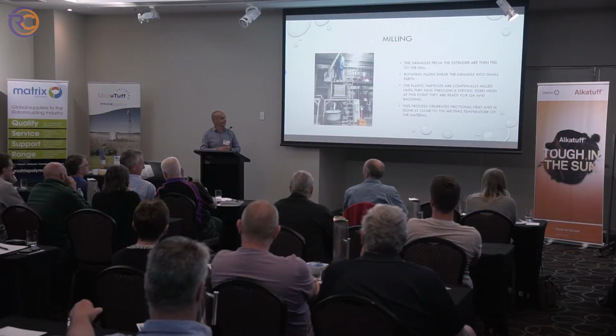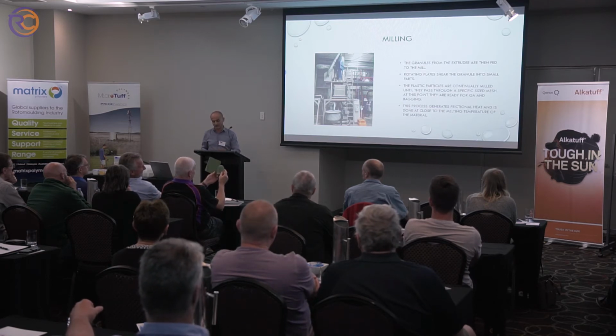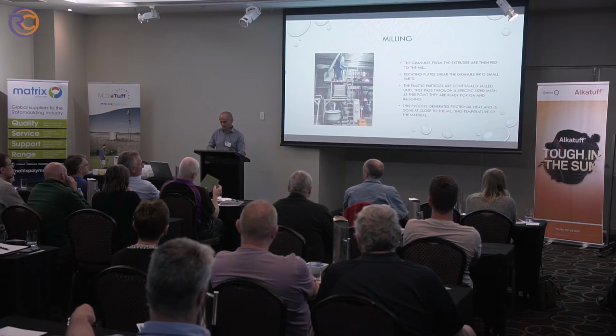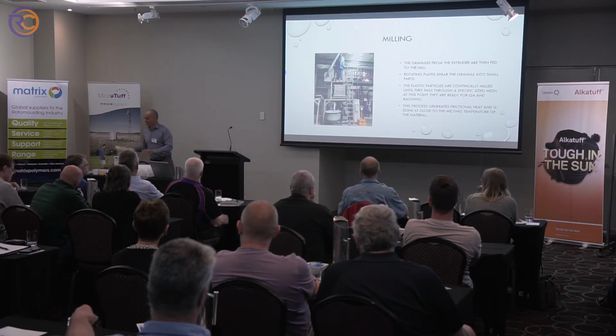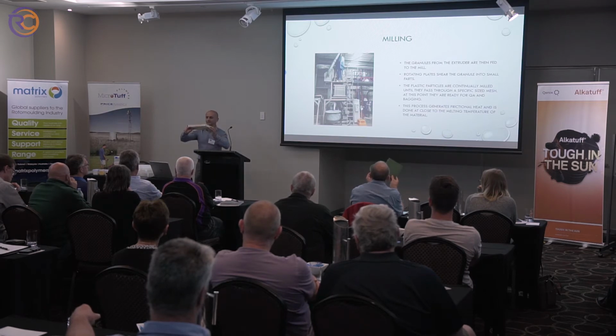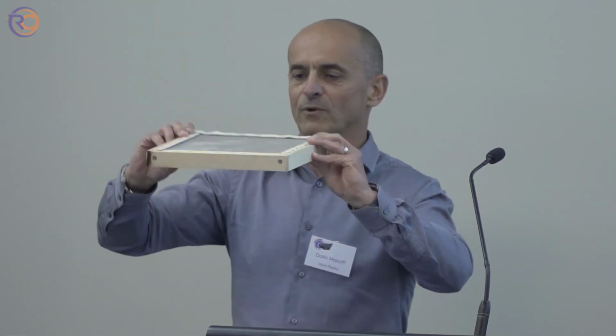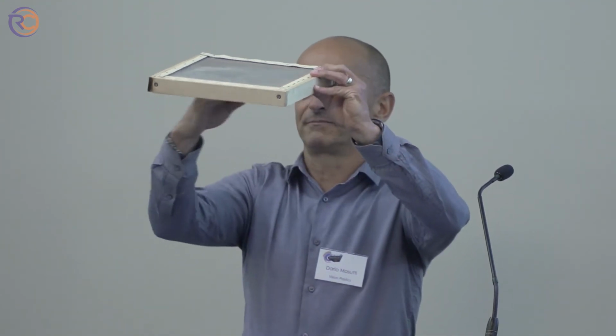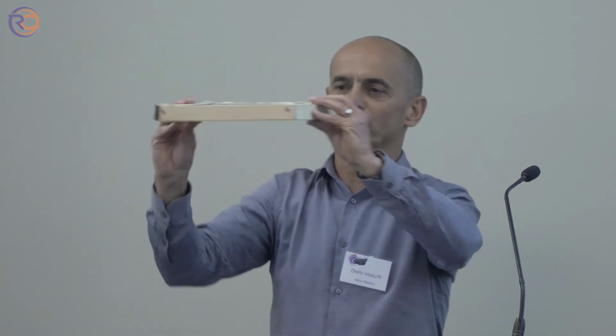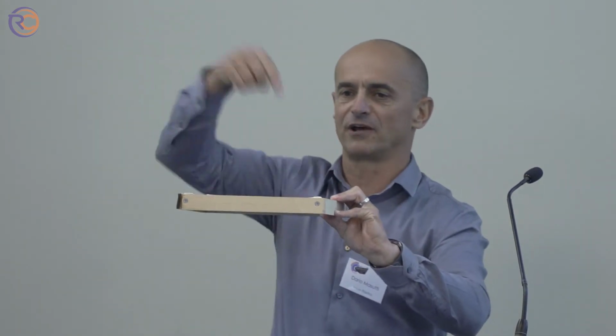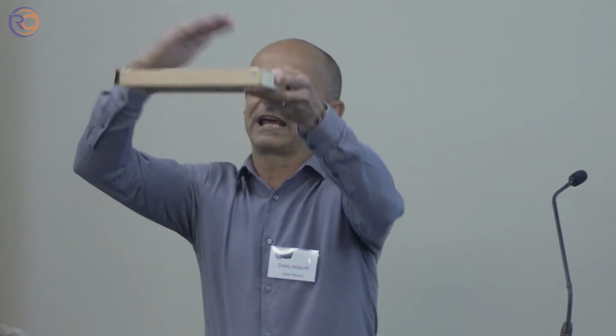The plastic particles are continually milled until they pass through the screen system, and all the oversized particles go back through the mill to get ground down if they don't pass through the screening. The process generates a lot of frictional heat, and it's done very close to the melting temperature of the resin. I've just made up a little example of one of the sieves, and what you have is mesh on the top and some mesh on the bottom to hold the balls in place, and these balls, as the sieve's rotating, help the powder flow through the screen or the mesh. You might have several layers of screens in one mill setup.